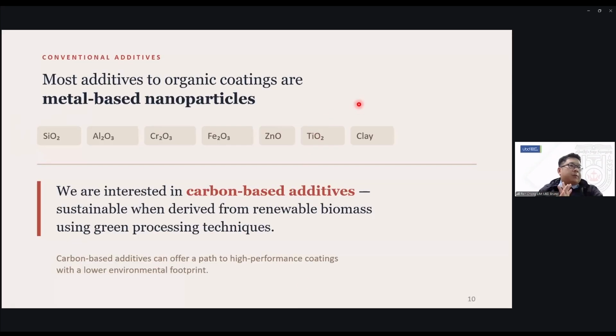In the past, people have added a lot of types of additives, but most of the additives in the past are normally metal-based. You see silicon oxide, aluminum oxide, chromates, even iron oxide, zinc oxide, titanium dioxide. They are added to improve barrier protection, corrosion resistance, UV protection, and mechanical strength. Clay also is added—clay is a kind of magnesium aluminum silicate that sometimes people add.